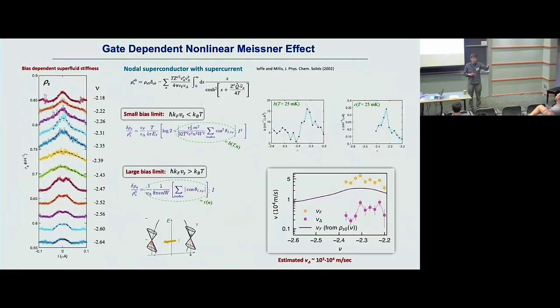However, barring that part, I don't think the linear temperature dependence is affected by the disorder too much, in the following sense. Usually you can take this linear slope and add disorder, and it smushes out, making it less linear. That's a huge issue in cuprate physics. Once you include disorder, usually you get more non-linear changes rather than linear changes. But starting with the nodal physics, creating linear slopes in the superfluid stiffness is rather difficult. So it usually works the other way around.